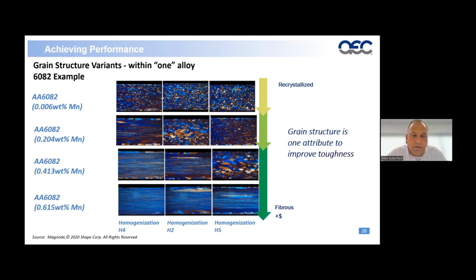So the production of a fully fibrous grain is more complex, slower, and more costly than the grain structure we see in the upper right. And that changes relative to the complexity of the material flow within the extrusion dies themselves. The more complex the hollow, the more complex the material flow paths within the extrusion dies, and relative to the reduction ratio of the presses, it can change the cost impact that one grain structure may have over another. This is one area where I see a gap of understanding that can have a significant impact and an opportunity relative to cost, and not only cost, but also product performance.